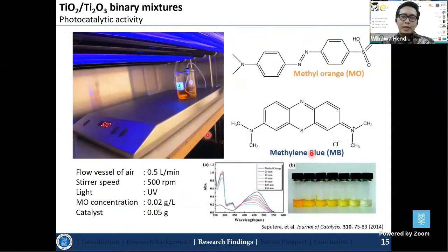And it can be seen in here that by increasing the reactions times, the colors of the dye is changing from the orange colors into the colorless. So it seems that the photocatalytic reactions appeared and the dye is successfully degraded by using the titanium dioxide and titanium trioxide mixtures.